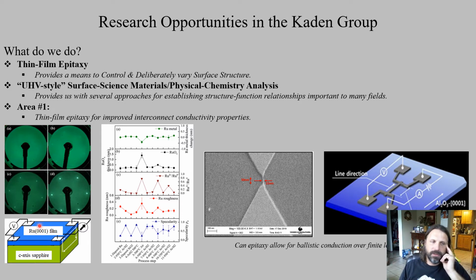One of the things we did there is we made a series of 4-point probe measurements for the thin films, which we can vary the thickness of, grown on the sapphire, to get an idea for what's going on with the resistivity. And we varied what we did to the surface. We would take the same sample and do all sorts of things to it. And we found we could get the resistivity to just jump up and down and up and down. But by monitoring the physical and chemical properties of the film at each step, the first thing we were able to learn is that we could selectively tune the resistivity up and down, and that came down to what we figured from our characterization. What we were changing was surface quality.